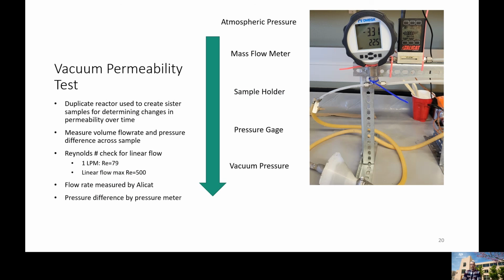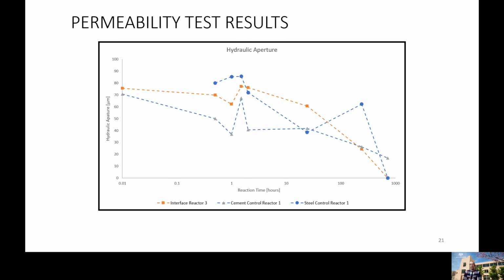Then we completed a duplicate reactor where we didn't seal them, and then measured the permeability after the reaction, and we did find that the permeability is decreasing over time. And this can be good because this can show that wells will decrease the emissions of greenhouse gases over the life of the well if there is a mechanical failure followed by the influence of this produced water brine.